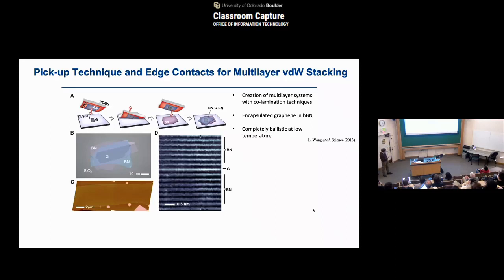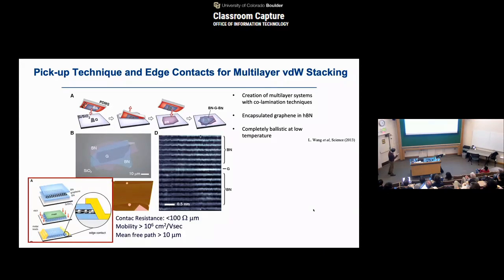But on top of that, when you put them together with the right shape and right geometry, it allows us to selectively etch the crystals in these stacks and address each of these atomic layers by outside electrodes, which means that even though some of the crystals are very close by, atomically close by in a 2D system, we can carefully address each individual layer by means of device fabrication. And that's another very important capability we have.